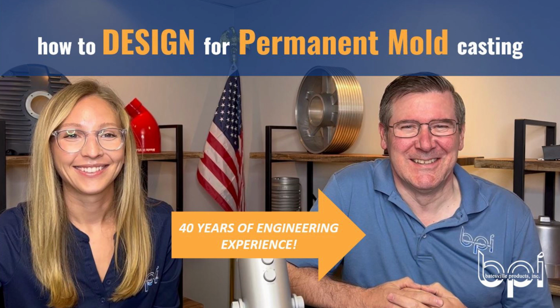You don't get the tolerances that we talked about for position and concentricity and our flatness out of perhaps a sand casting process or some other casting processes, but the permanent mold process using steel molds is capable of very, very high tolerance parts, as you can see with this flatness. So for 0 to 6 inch size parts, it's flat within 20 thousandths of an inch coming out of the mold, and then you add 2 thousandths for each additional inch.